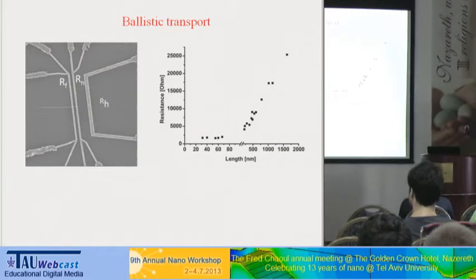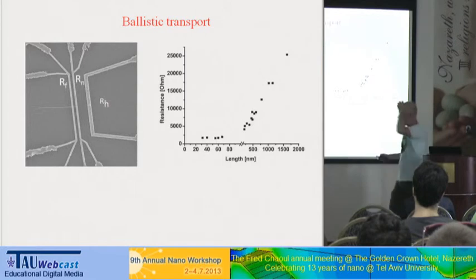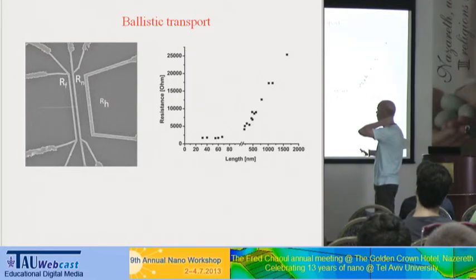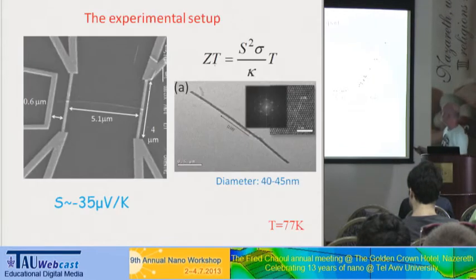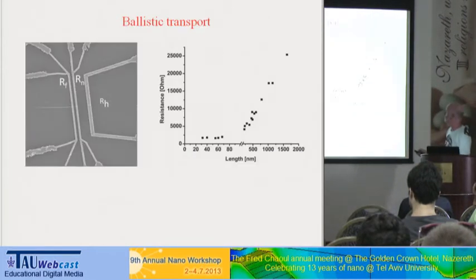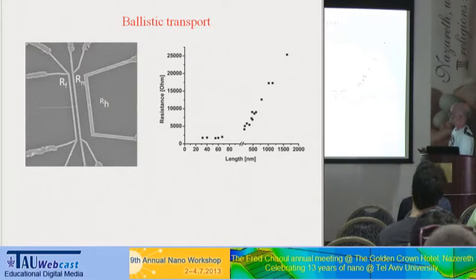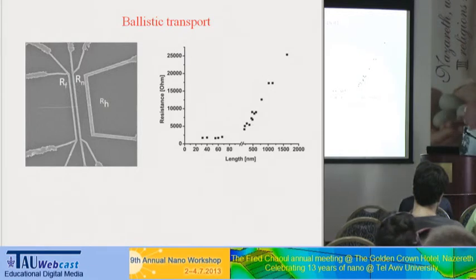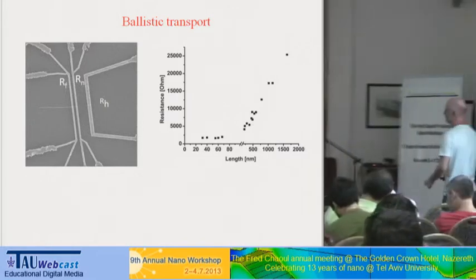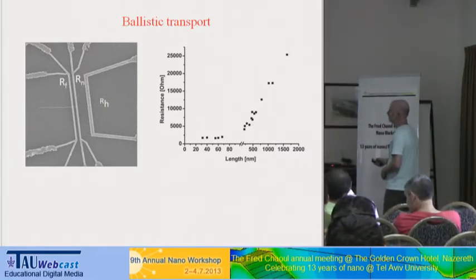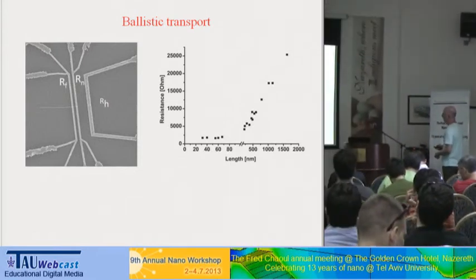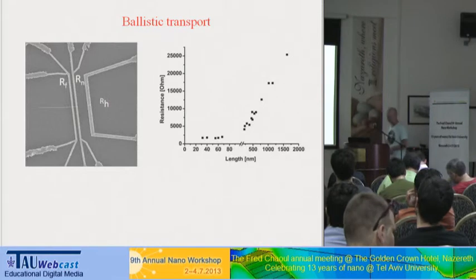Now, the next thing is that we want everything to be ballistic. Why? I'll show you in a second. So we simply push the 2 contacts on the bismuth nanowire. Instead of being here on both sides, we push them to be really close to one another. And then we make the 2 contacts at different distances, and we measure the resistance as a function of this length. You see that for certain distances, it becomes ballistic. The resistance is not changing. So every electron that is coming from one side is going all the way down to the other side without any scattering. So we want to work in this regime. So all the experiments that I'm reporting from now on are with contacts within this length range.